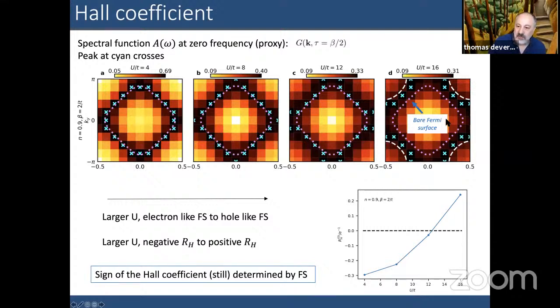The bare Fermi surface is given by these pink dots. Of course, as U gets small, the Fermi surface matches up more closely with the non-interacting one. But as one increases the value of U, we go from a Fermi surface closed around gamma to one closed around pi, pi. The crosses here show the peak of the spectral function for all of the momenta that we get access to in the cluster.